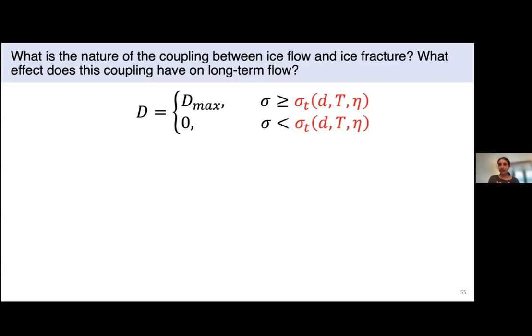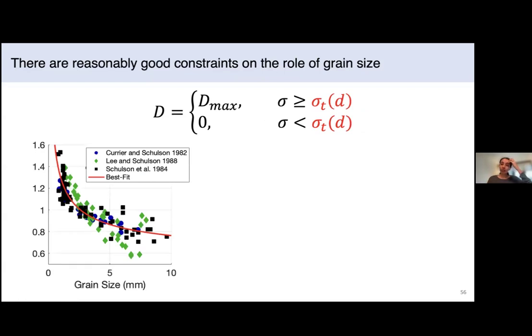So we were interested in producing an ice strength equation that has dependencies on a whole lot of things like grain size, temperature, or viscosity. Unfortunately, we are constrained at the moment by the existence of laboratory data, because otherwise there's not really much to base an equation off of. And really the primary good constraint we have on ice strength as a function of anything is grain size. There have been three primary studies that have looked at how ice strength varies, and that's what should be on this y-axis. I keep needing to fix that. Ice strength in megapascals should be on that y-axis.